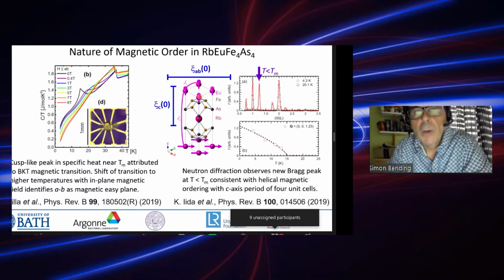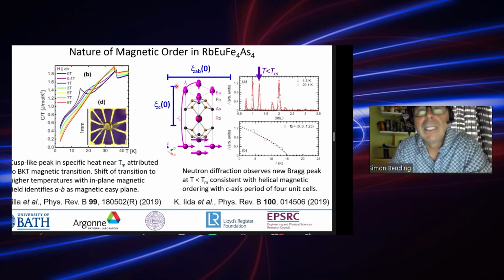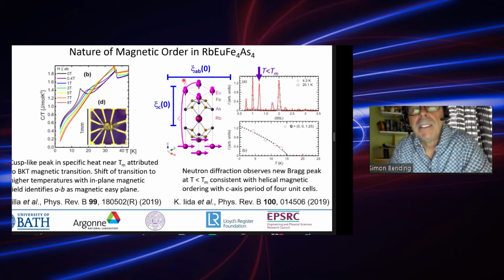But you can see it is quite small. It's of the order of half a unit cell size. And if you look at this, you immediately appreciate that the superconducting electrons which reside here in the iron arsenide planes must actually have significant interaction with the Europium moments here at the top of the unit cell.